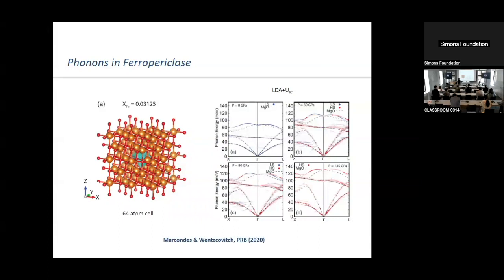More seriously, 2 questions. One is, how sensitive is this to the value of U? I mean, this is DFT plus U, right? So where does the U come from? U is calculated by linear response. The interesting thing is, vibrational frequencies don't depend so much on U, or on the functional, but that's a second order effect on the free energy itself. They affect the transition pressure, for sure. You can move the transition pressure back and forth because that's at the point where the enthalpy difference is zero.